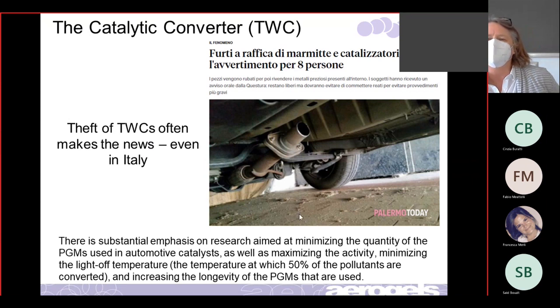So there's a lot of research aimed at either minimizing how much of the PGMs you use, as well as maximizing the activity. So that means more active, that they catalyze better. So it just does a better job. Minimizing the light-off temperature. So the way that you characterize a catalytic converter is by defining a light-off temperature, which in this case is defined as the temperature at which 50% of the pollutants are converted. So if I started out with 100 COs, whatever temperature I'm down to 50 COs, that's called my light-off temperature. So it means your reaction is taking place. And then also increasing the longevity of any PGMs that are used.